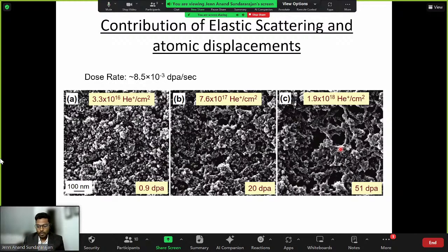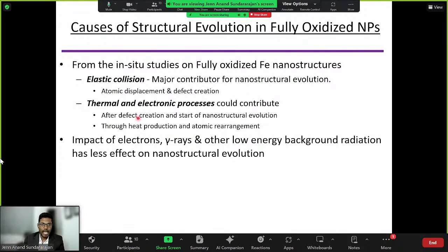So, in the end, what we can conclude is, yes, there is elastic collision happening. That is the major contributor to the grain boundary evolution and particle agglomeration. The next point is that the thermal and electronic processes do not directly contribute to anything, but they do contribute, one at a time, slowly, in terms of heat. That is all we want. So we took oxide particles, we exposed them to radiation, we saw structural changes, and we saw the magnetic properties change drastically. Now we understand that this is happening due to elastic collision aided by ion radiation and grain growth. Thermal and electronic processes could have contributed a little, but are not the ultimate contributor.